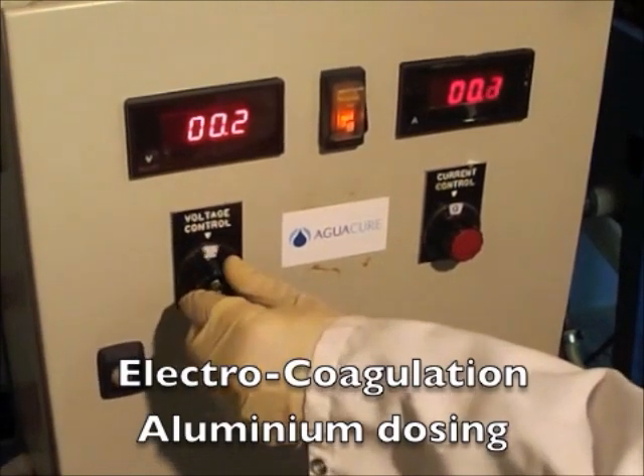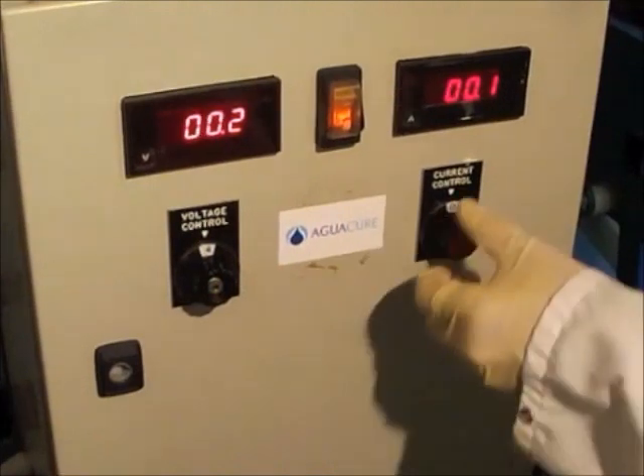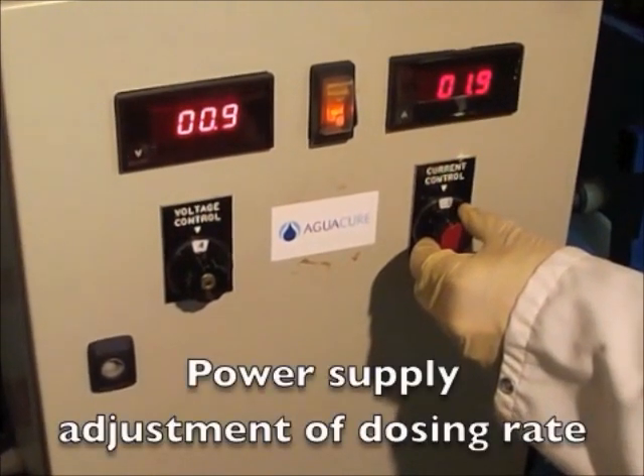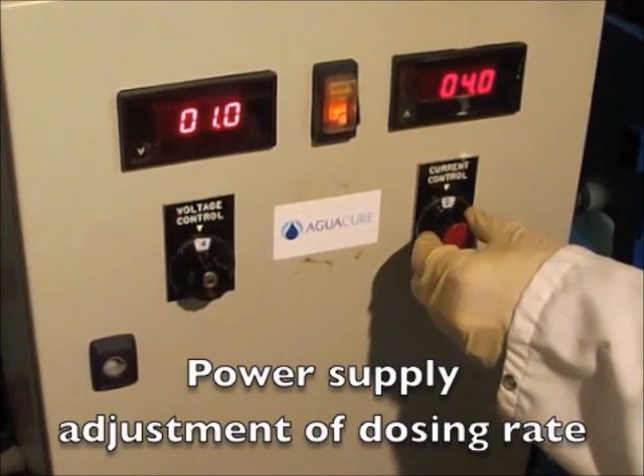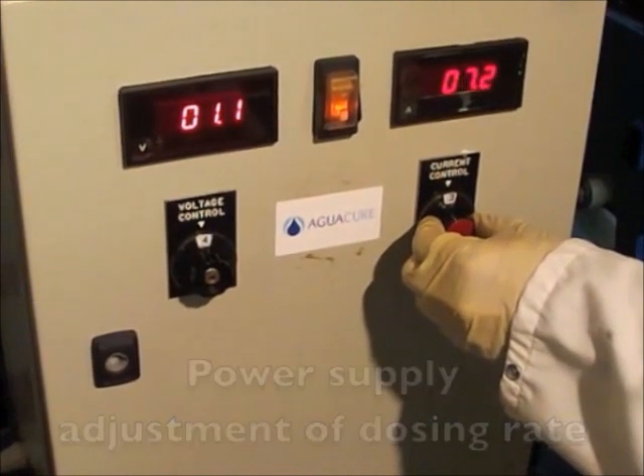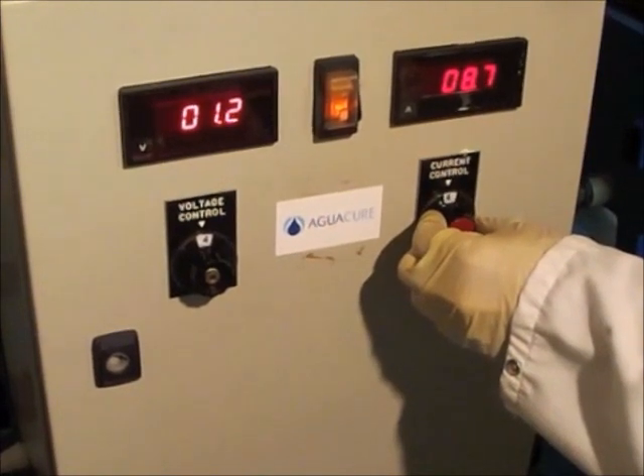The electrocoagulation cell developed for the Ecometre project is capable of reprocessing 10 metres cubed of solution per week. The rate of aluminium dosing is controlled to maximise nickel recovery and minimise energy costs.